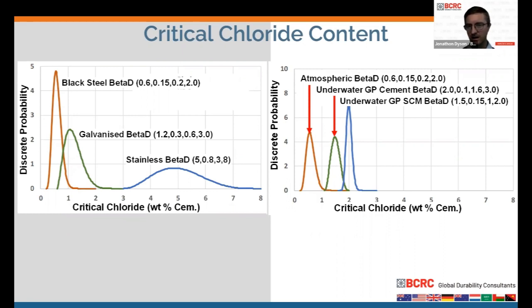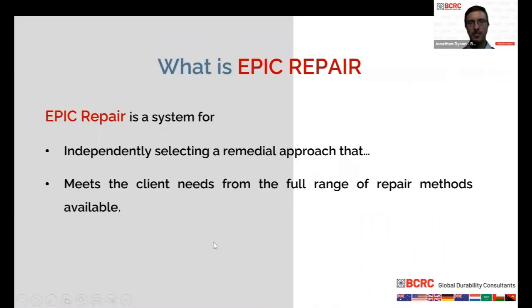In other structures, in other environments, with other concrete mixes, etc., and I'm talking about mild steel reinforcement here, you might have a structure in which you can get up to, say, 2% of chlorides by weight of cement before reinforcement will start to corrode. And that's what this sort of distribution here is all about. And that's so you use the distributions in full probabilistic analysis to get more accurate outcomes.